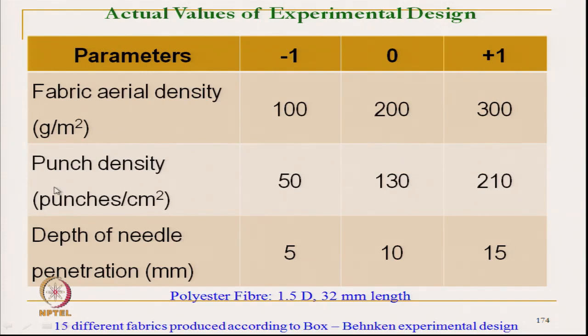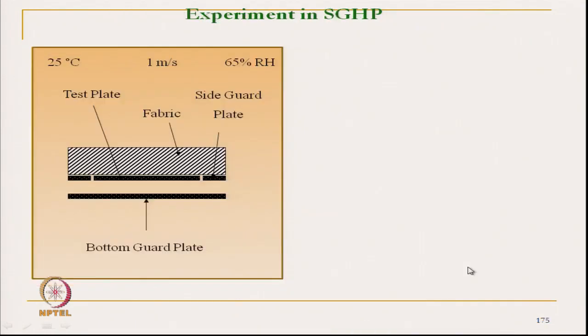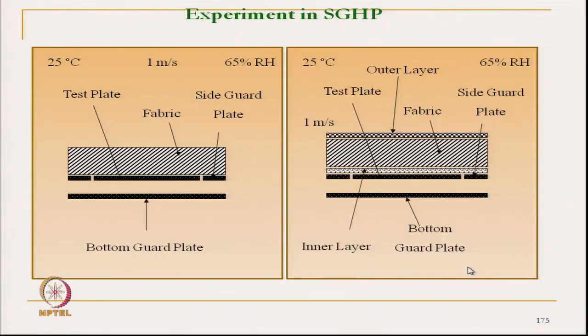model, where needle punch density is increased from 50, 130 and 210, a difference of 80 is kept here, and depth of needle penetration is 5, 10 and 15. So, with this experimental setup design, the nonwoven fabric is produced, and here